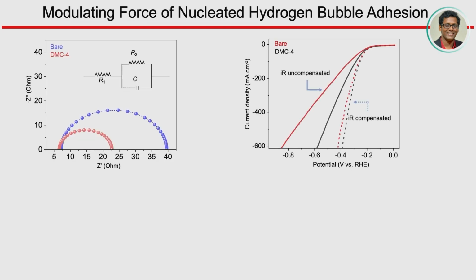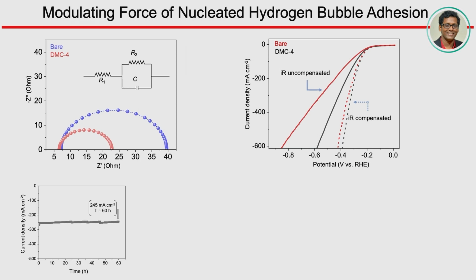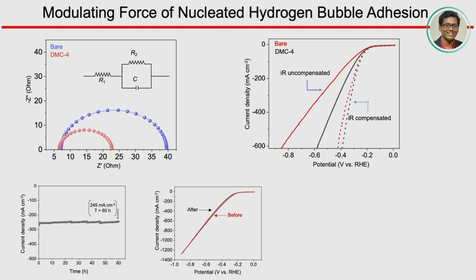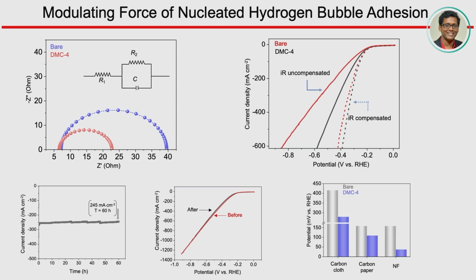So this is not the catalytic performance of the coating, rather how you play with the bubble dynamics. And you can see here the resistance, right? Whatever you have improved because of this coating, if you incorporate it in this LSV, then you see a similar kind of performance. So that again tells that this is not just based on the catalytic performance, it's just the resistance which is created because of the bubble adhesion. And once you play with that, you can minimize this overpotential, and this coating remains quite stable. Even after this stability test, we performed this LSV, and they remain nearly similar.